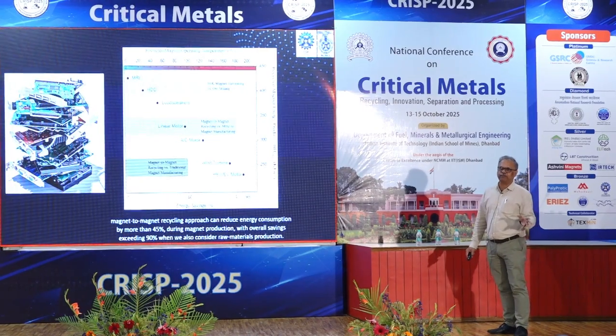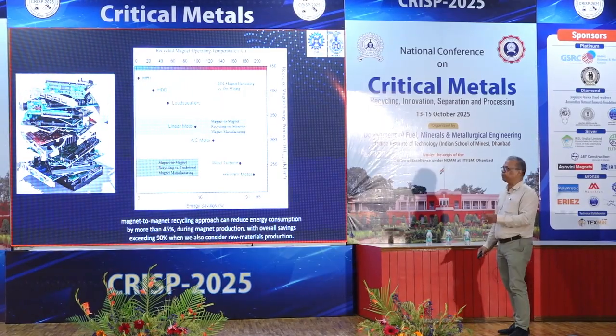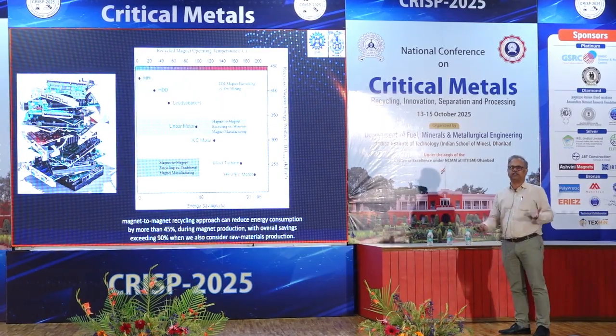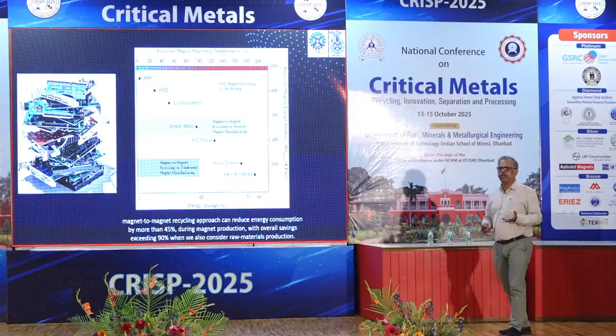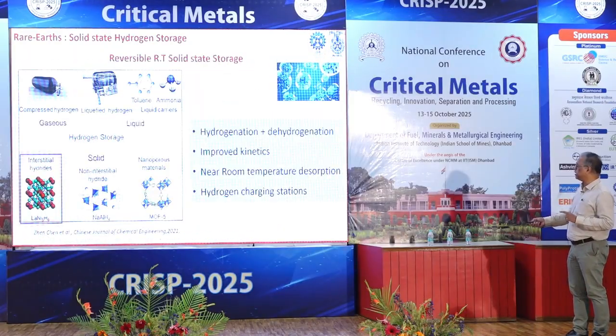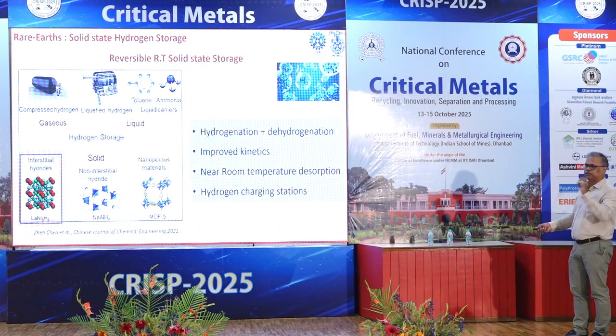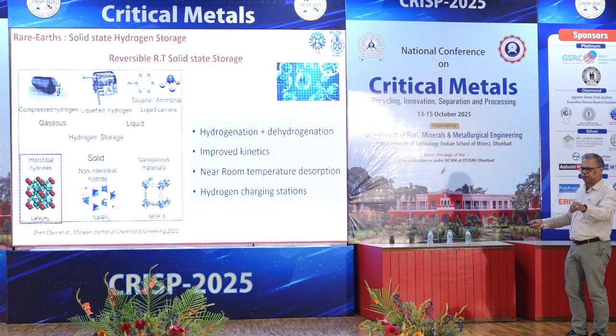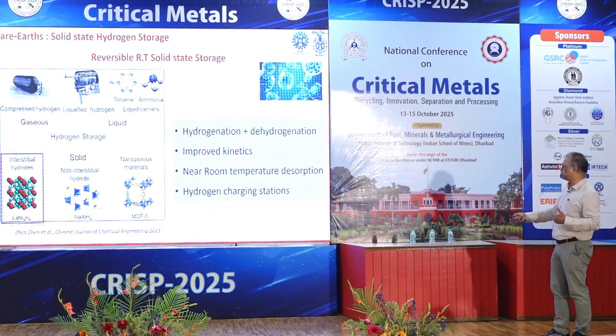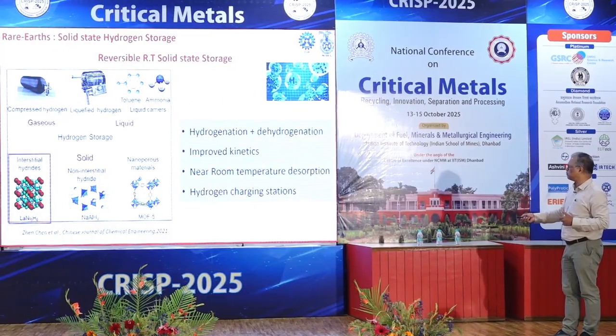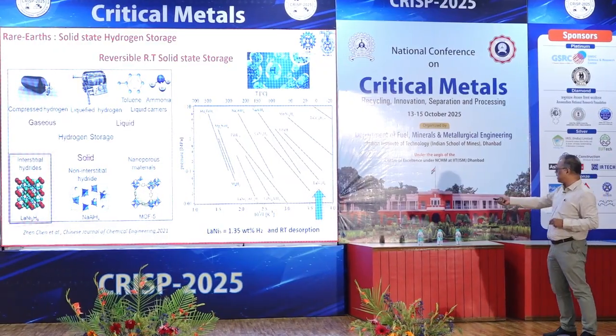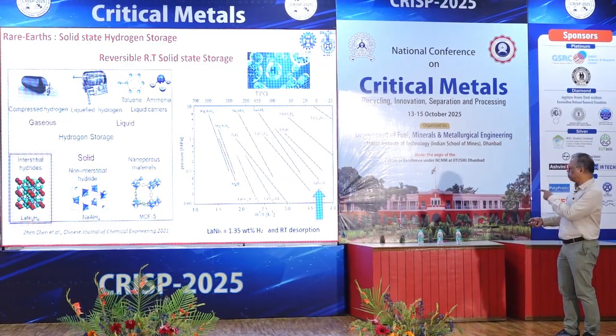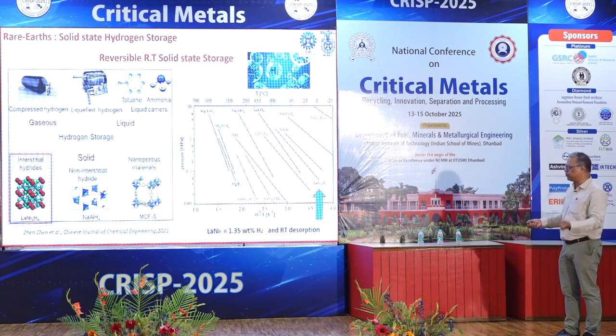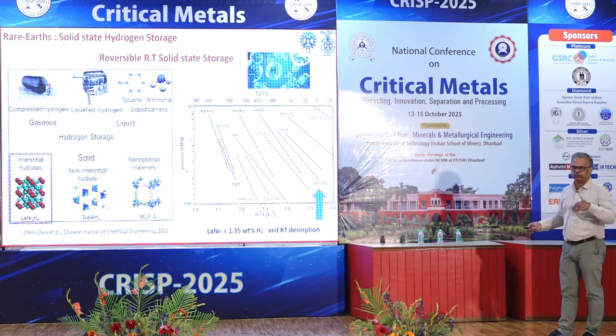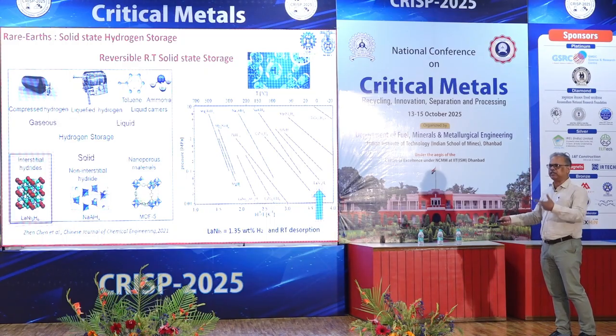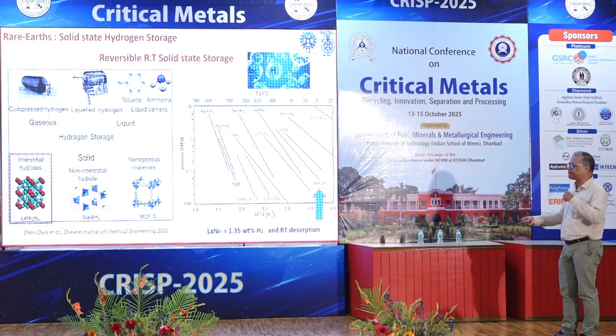Now rather than going from 0.02% to a concentrate, if I get 30% and then make the concentrate, it looks like the industry will be good. We also thought of using hydrogen storage materials, where you can put hydrogen inside by an absorption method and then have very fast desorption. These are the graphs: lanthanum nickel hydride can absorb 1.35 wt% hydrogen, and desorbs at room temperature. So you don't require any temperature or any release of pressure to get the hydrogen back.